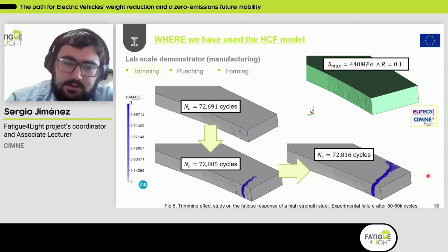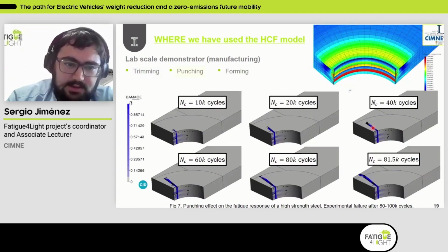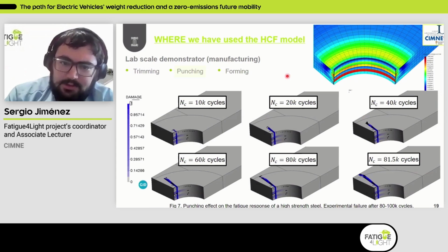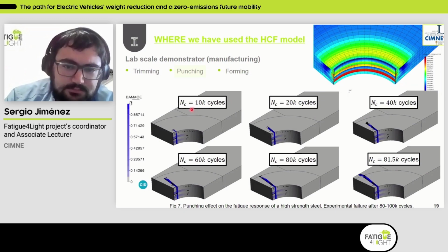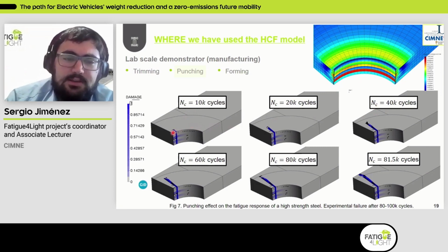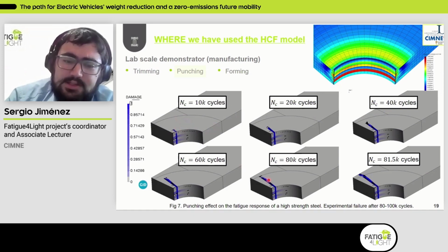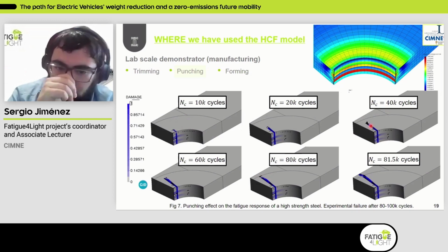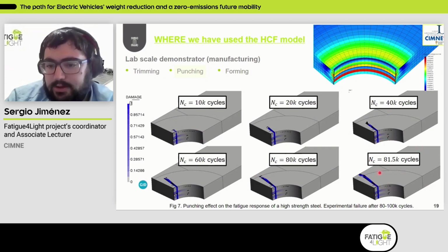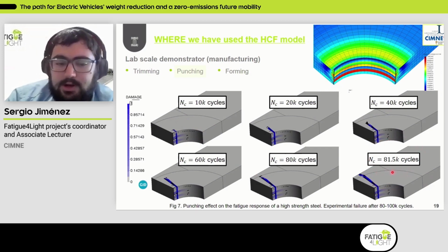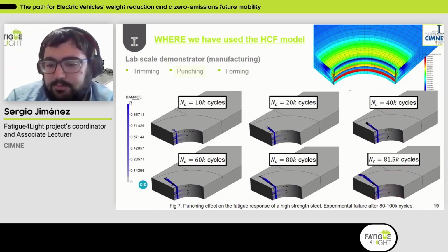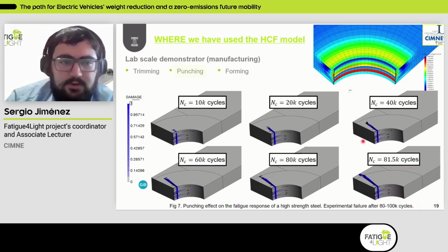But we can, of course, take into account residual stresses, and this is what I'm showing here in this punching example. So basically, we have the information of the residual stresses in this punch area, and so we incorporate this information in our simulation, and by doing that, this is the effect that it has on the evolution of the crack observed along the simulation. And you can see here the final failure of that sample obtained after 81,000 cycles, which matches with the experimental results obtained for this type of sample.